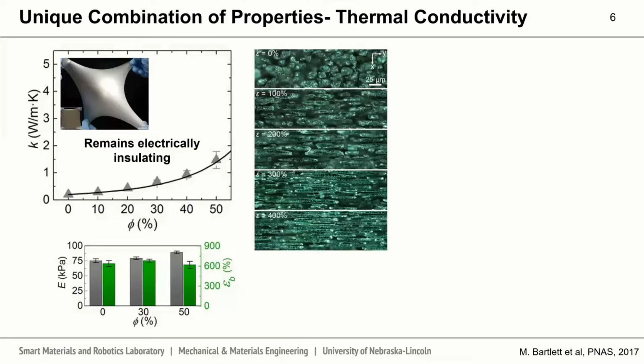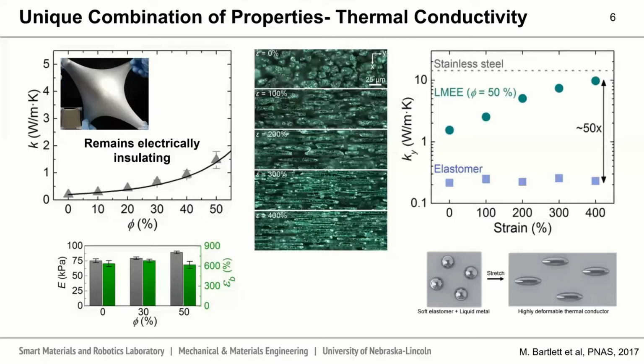Due to the liquid phase nature of the filler, the liquid metal droplets actually deform along with the elastomer matrix as a function of stretch. So here, the top image shows spherical droplets in the elastomer matrix. At the bottom image, at 400% strain, you see long needle-like inclusions. And if we were to measure the thermal conductivity in the direction of strain, we actually see a significant increase as compared to the base elastomer matrix.